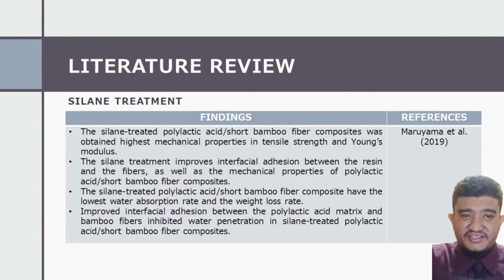Next chemical refinement method is silane treatment. From the finding, the silane treated polylactic acid short bamboo fiber composite obtained highest mechanical properties in tensile strength and Young modulus. The silane treatment improved interfacial adhesion between the resin and the fiber, as well as the mechanical properties of the composite. The silane treated composite have the lowest water absorption rate and weight loss rate. Improved interfacial adhesion between the polylactic acid matrix and bamboo fiber inhibited water penetration in silane treated composite.